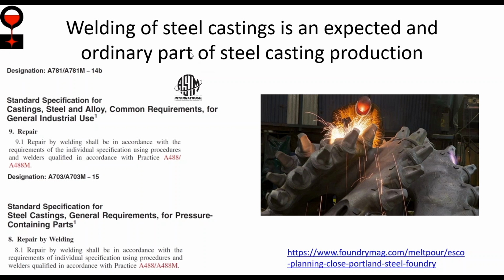Most steel castings are ordered to ASTM grades. The ASTM grades all have the common requirements grouped into two different specifications. One of the specifications is A781, and that's for common and general industrial use. The other is A703, which is for pressure containing or more critical components. But in both cases, they specify repair by welding, and they reference A488. And so we, in steel castings, if you order to ASTM, the foundry is permitted to use welding to make sure they achieve all of your requirements. But they can't just weld willy-nilly with any guy that they hire off the street. They have to comply with ASTM A488.